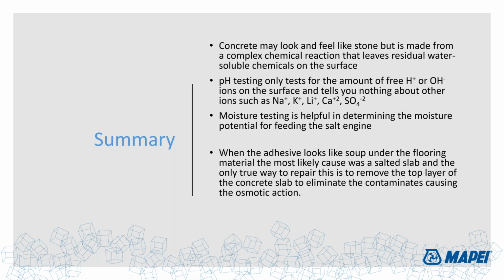Again, moisture testing is also important. It pretty much tells you the potential for feeding the salt engine. Osmosis is going to keep going. These salt pumps are going to keep functioning as long as there's moisture to pull from. So a highly moist concrete slab at the 99% level is like saying I've got a really deep pool of water, and this salt engine has a full tank of gas and is going to run for 540 miles. As opposed to something that's a little bit drier, with moisture testing numbers of 75% RH and maybe 3 pounds of moisture vapor emission, where the tank is quarter full, then it's not going to be a problem.